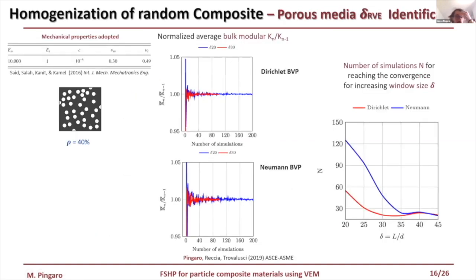For the reason described, we focus the attention on the porous media, and we consider a material with a very low contrast. The adopted mechanical parameters are reported in the table. And first, we study the case of high average density, that in this case is the porosity of the material.